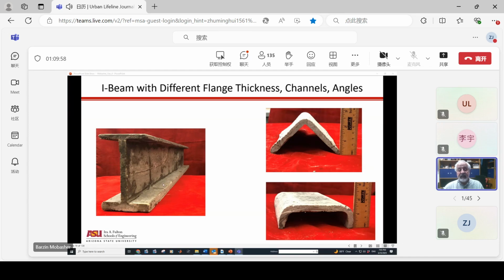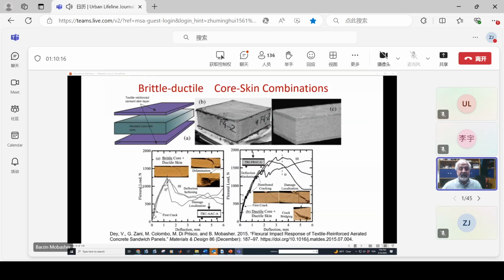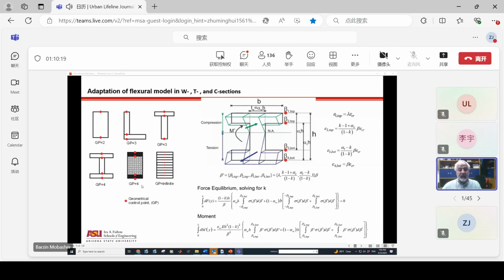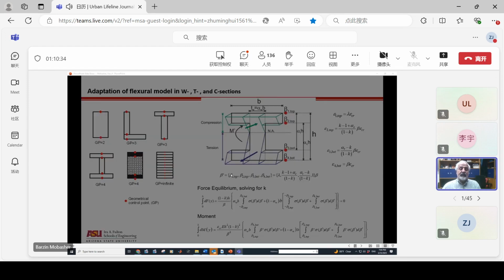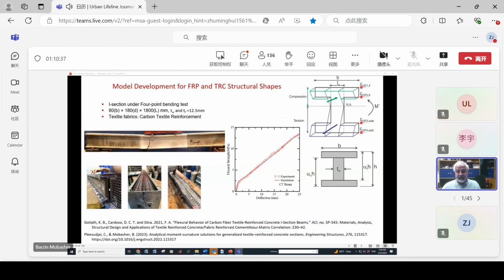Another area that we've done is going with W sections, angles, channels, and in all of these systems, we're using the model that we have to simulate the results of the tension and the flexural response. Sandwich composites, all of these systems fit into this design methodology that we have developed using the flexural model, whether we use different control points. Now we can do sandwich, W sections, angles, and such. So the solution strategy is now developed for us to make W sections with textile reinforced concrete or with UHPC and test them in tension.